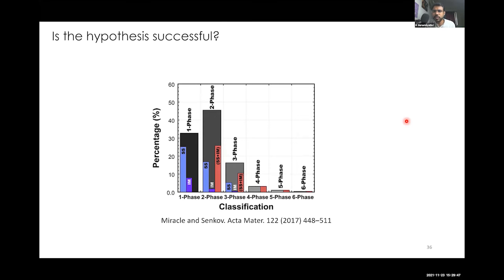This one slide tells you whether the hypothesis is successful or not. Okay. So let's see this one. How many percentage of cases? This is coming from around 640 microstructures of experimentally verified high entropy alloys. And this is their result. The percentage of systems which have one phase is about 33%. Systems which have two phases are almost 45, 46%. And there are systems with three phases, four phases, five phases, six phases also.